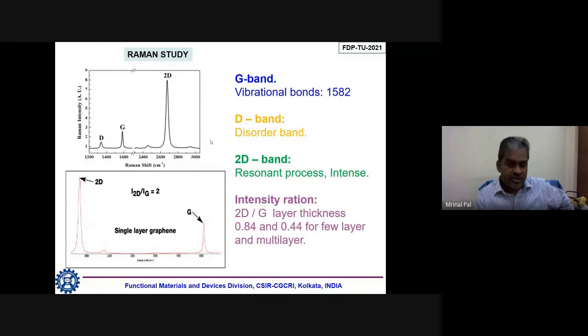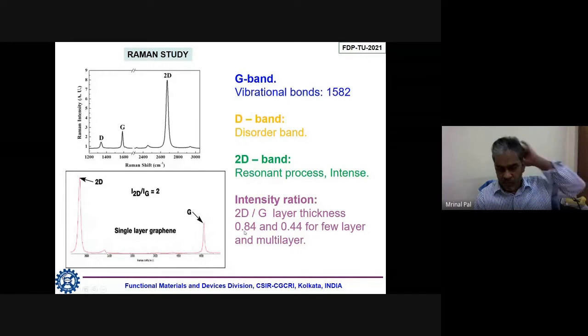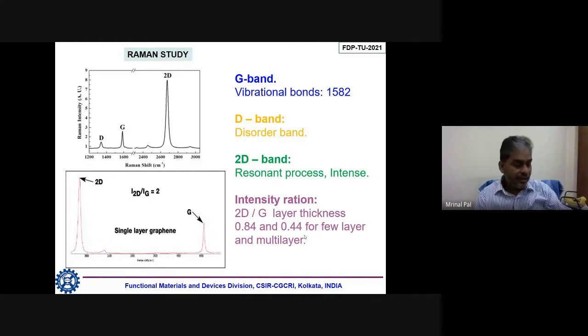Raman study is one of the important studies. If it is really a single layer, then this intensity ratio of 2D and G will be almost 2. But if it is few layer, then it can be below 2 and it can be like 1 or 0.84. And if it is very low, like 0.4 or less, then it will be multi-layer. So by showing the intensity of the 2D and G peaks of Raman study, one can in principle guess how thick the 2D material prepared in the laboratory is. That's why Raman study for 2D material is very, very important.